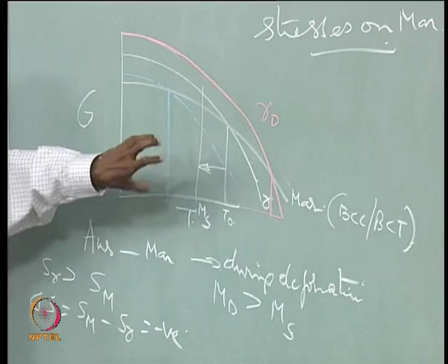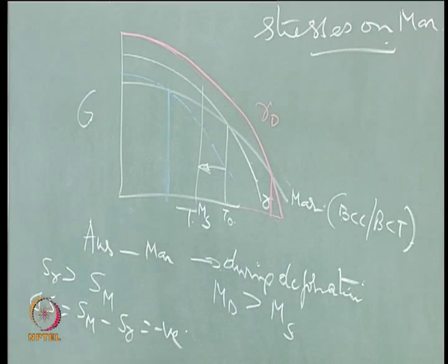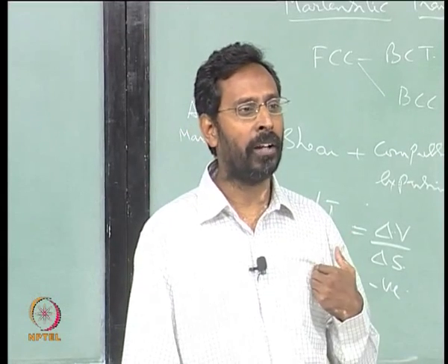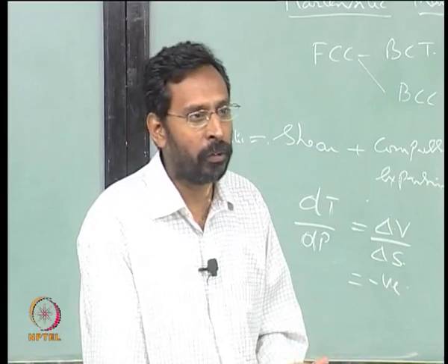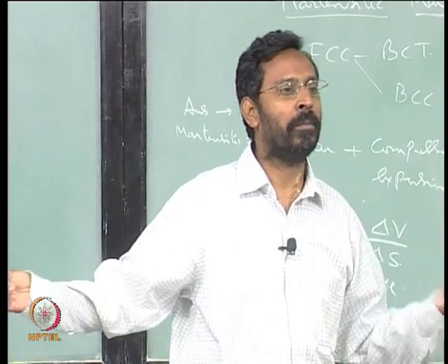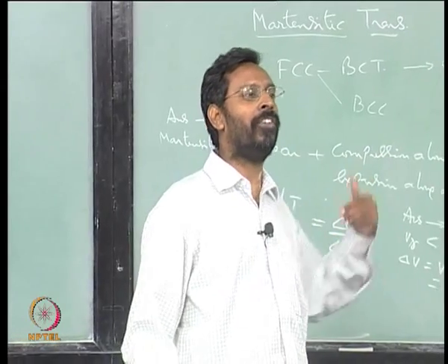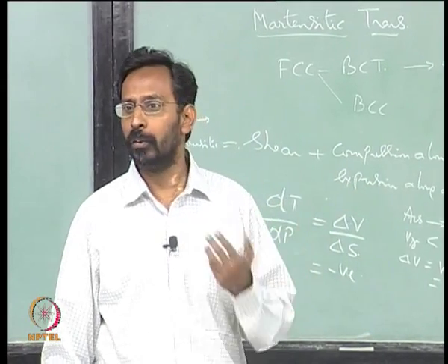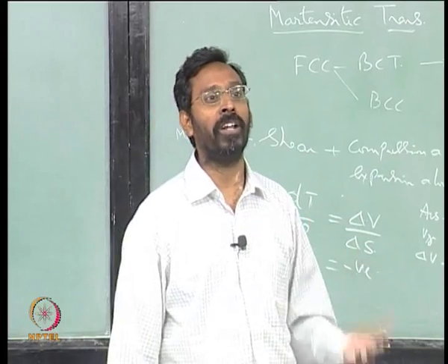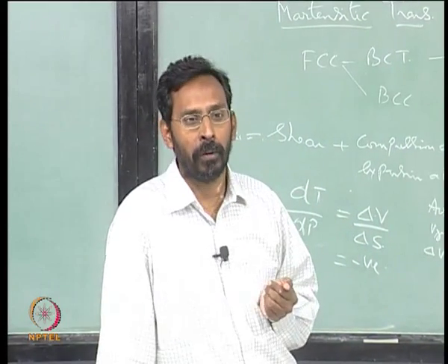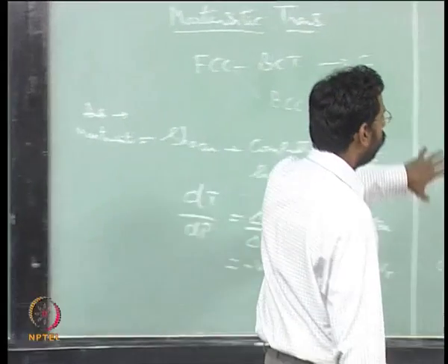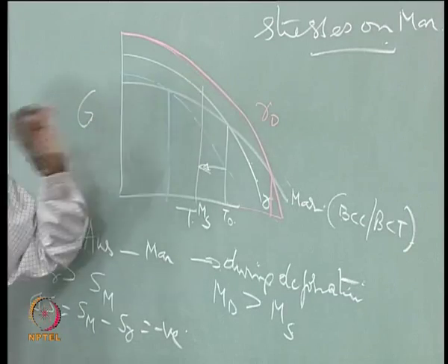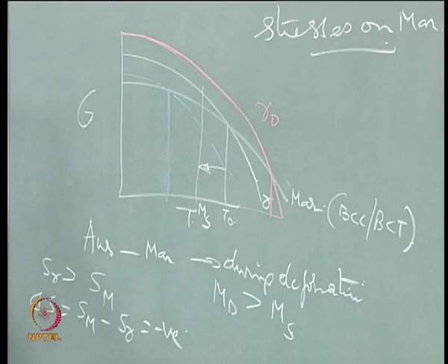Okay. So, in case you are dealing with powders and doing hipping or sipping of them, and then trying to see whether you get a martensitic transformation, you may say why should I bother about what temperature it will transform. I need to bother about it because I need to know to what temperature I should bring it, if I want to get 100% martensite. So, if MS itself is low, MF will also be low. So, to get 100% martensite, you need to go to a much lower temperature, sometimes even sub-zero. That is an aspect which you need to understand. So, the pressure brings in this effect and that changes the free energy, and as a result the whole transformation changes.